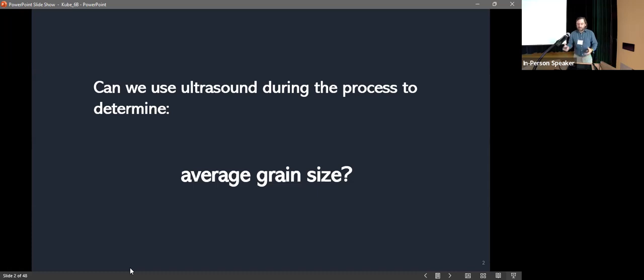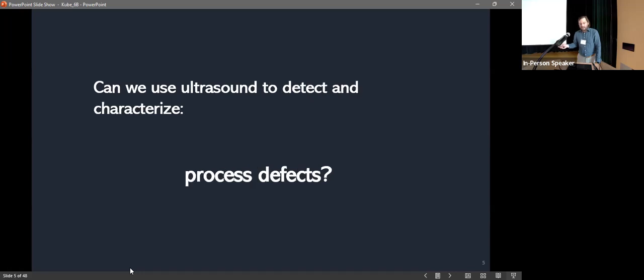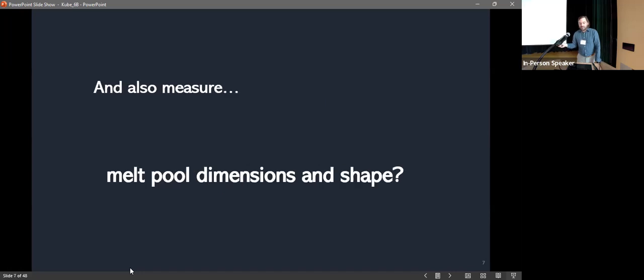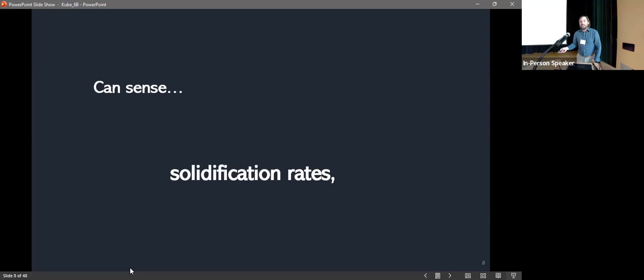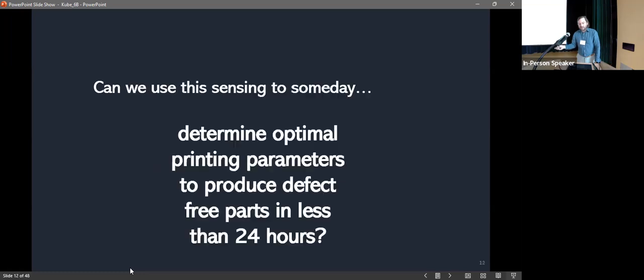So this opens up the door to answer a number of provocative questions. The first three are for in-process part monitoring. Can you use ultrasound to measure average grain size? Can you get information about the phases present, residual stress? On the melt pool side, can you sense process defects that form, such as the porosity Jay was mentioning, melt pool dynamics, melt pool dimension and shape, solidification rates? All of this is beneath the surface. Solidification, cracking, pore formation, microstructure formation, and so on.